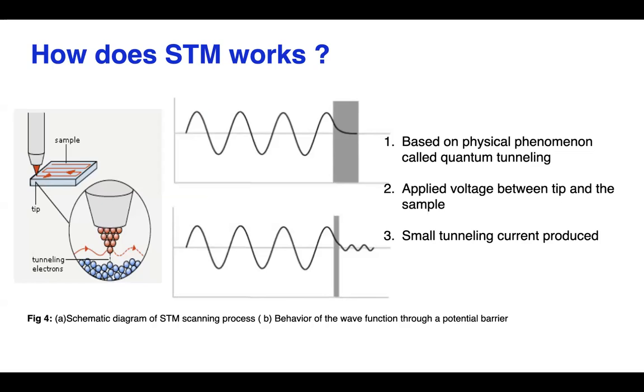in quantum mechanics. So here you can see 2 diagrams. The gap between the tip and the sample acts as a potential barrier in quantum tunneling. If the distance or the gap between the sample and the tip is large, then you can see the electronic wave function dies out within the potential barrier. So we won't get anything out of that. We don't have any information out of it. Therefore, that is the main reason we have to keep the gap between the STM tip and the sample in the nanometer range.